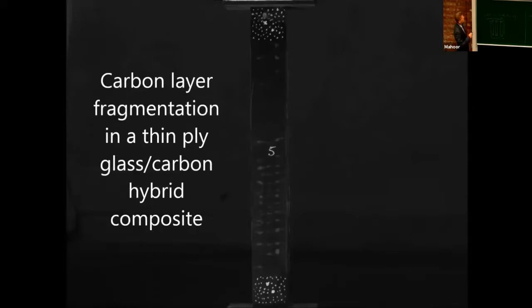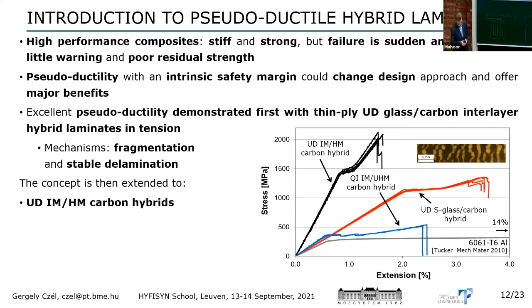So you can see through the transparent glass epoxy layers that the carbon fiber breaks at several locations along our composite, and then these lighter spots or lines indicate the local delamination around the carbon epoxy layer fractures. And this concept was first shown for glass and carbon hybrids in a unidirectional structure.